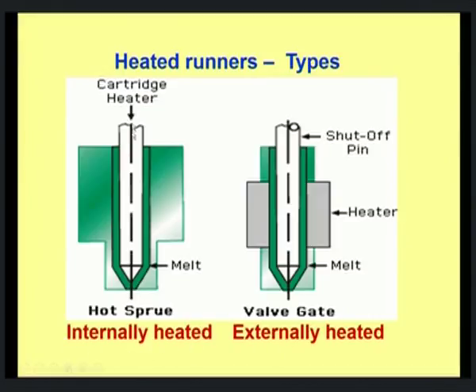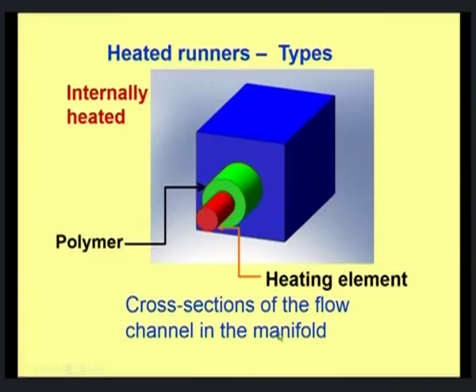First, the internally heated: you could see the cartridge heater is provided in the flow path itself. This is the passage for the melt, this is the runner, and the melt flows through this runner. In the passage itself, the heater element is provided. That's why it's called internally heated. Whereas in the externally heated, you could see the heater is provided externally. It's not located inside the runner. Rather, the heater will just surround this runner, and there should be insulating features that will insulate the heat transfer from this melt to the rest of the mold. So, this is again the cross sections of the flow channel in the actual manifold.